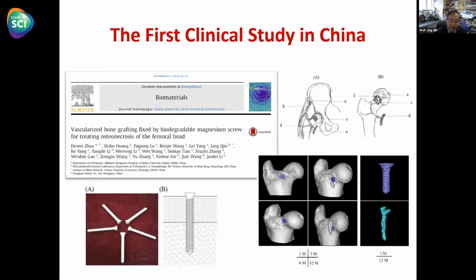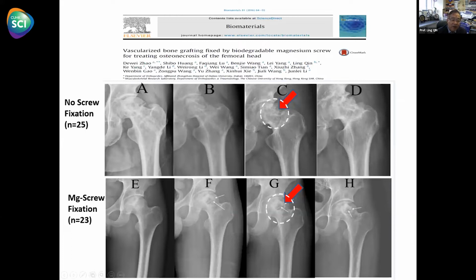This is a magnesium screw after implantation to fix the bony flap. We see the baseline, and 12 months later it has degraded with time. Compared with the conventional one without the screw, with the screw we see degradation enhances the bony flap bone mineral density, which means it makes the implanted bone vital.